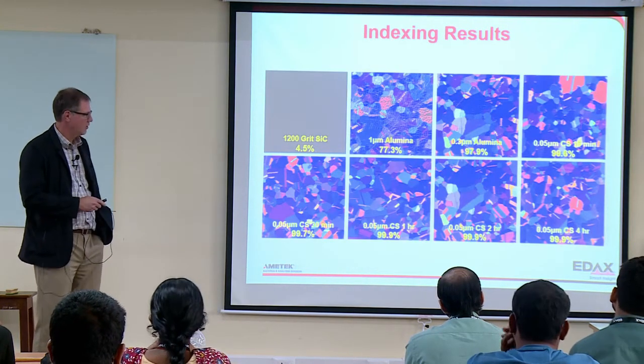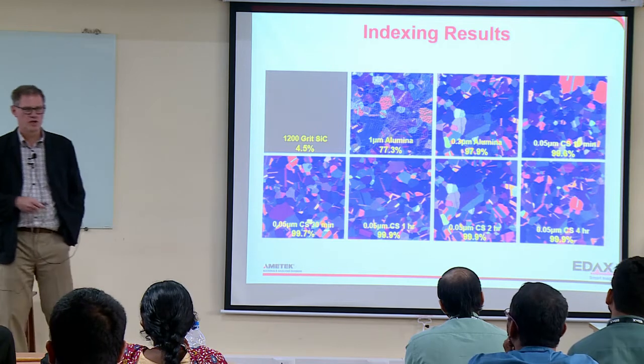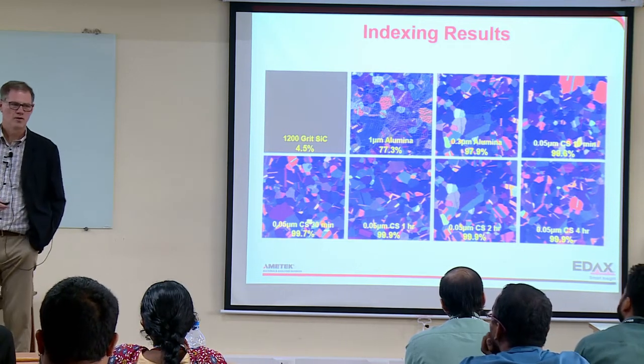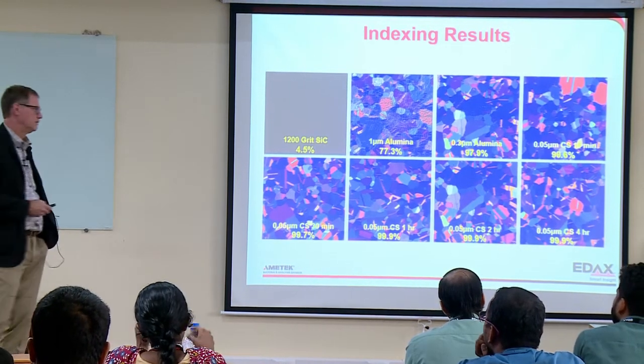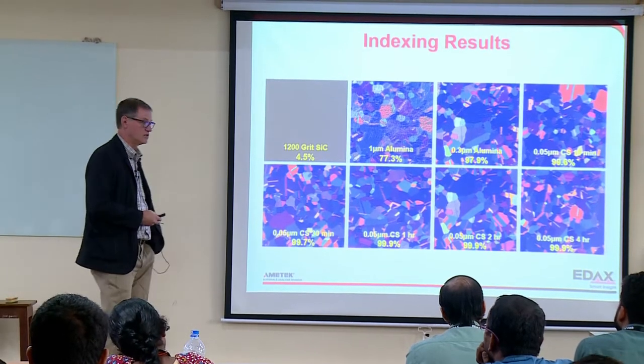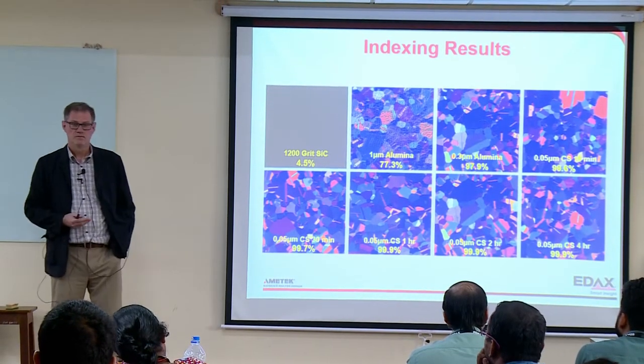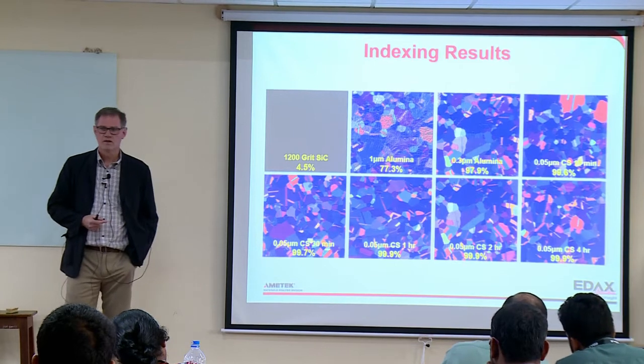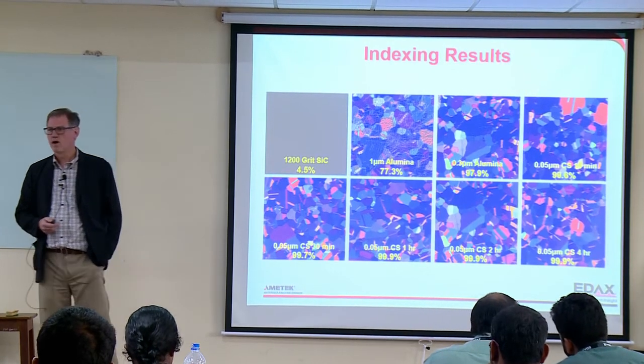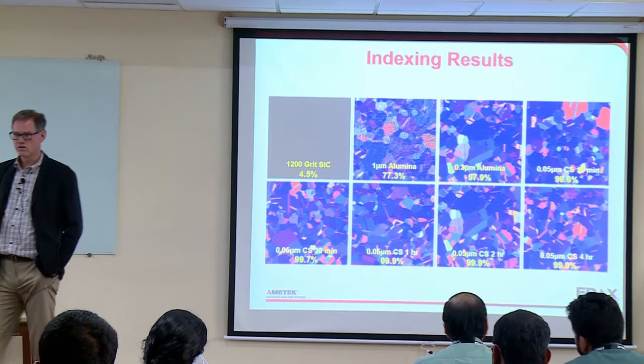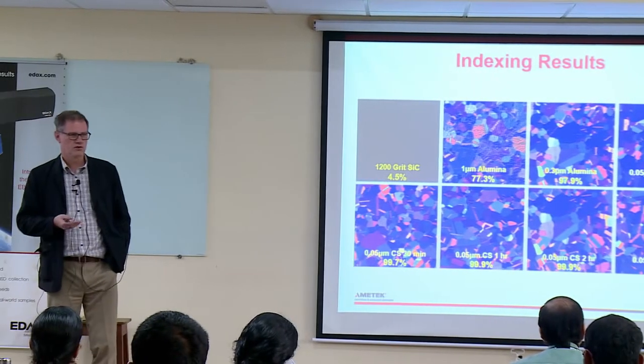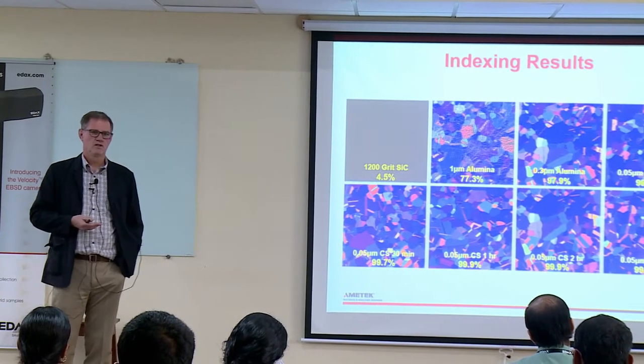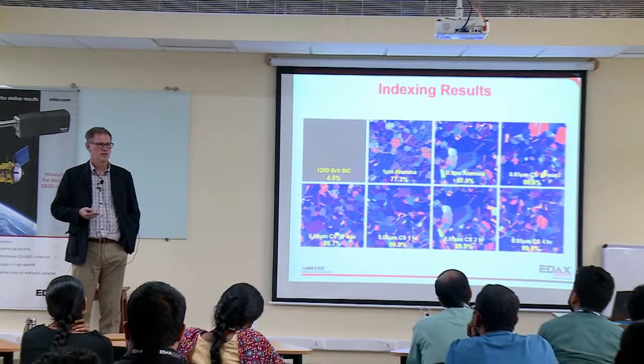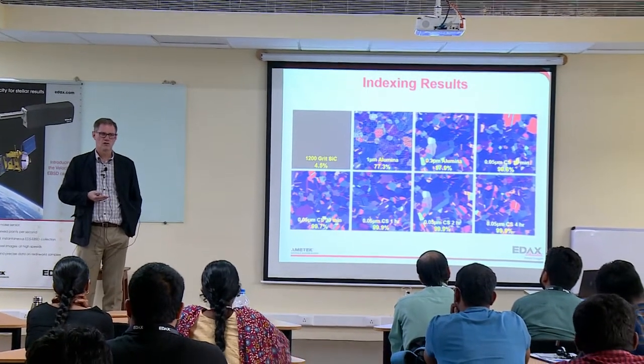Just another word or two. I'm showing mechanical polishing results. You can use electrochemical approaches, and they work great. The other thing that people are using is a FIB, which is great if you have access to a FIB, or a broad beam ion polisher. It's just that if you use the FIB or broad beam ion polisher, you'll need to not be too aggressive. You need to work maybe at lower voltages and use a glancing angle, because that will improve your results quite a bit.